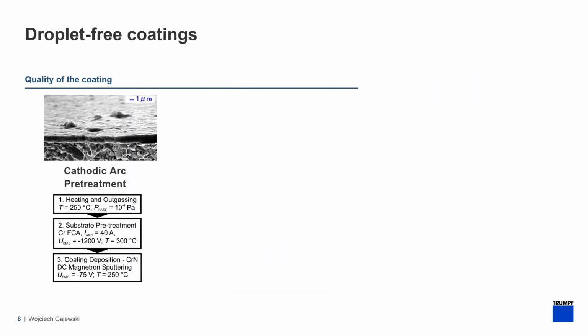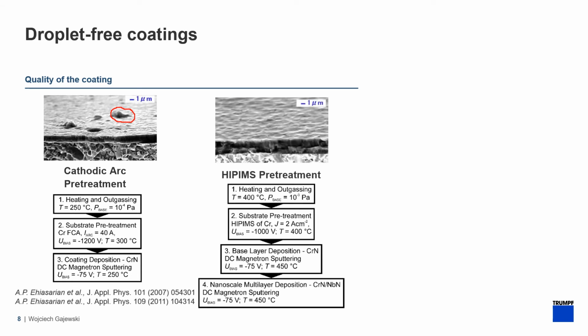Another advantage of HIPIMS is also related to the quality of the coating. There are processes using cathodic arc pretreatment. These processes are even much older than processes with HIPIMS. And with those you can also get a decent quality of the coating, for example used for cutting tools. However, these coatings always have the problem of defects from macroparticles in them. To change this situation, you could use the HIPIMS pretreatment, which will also give you high ionization of the plasma, but you will get a coating without such defects from macroparticles.